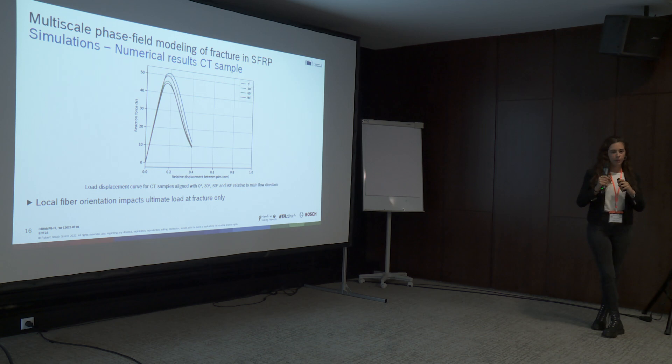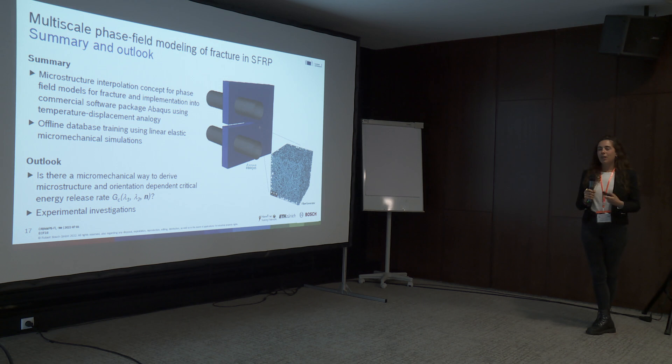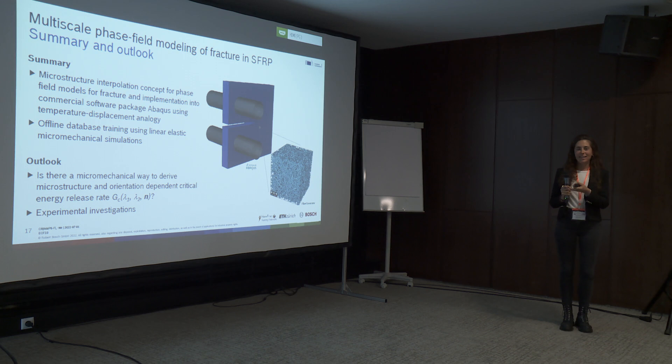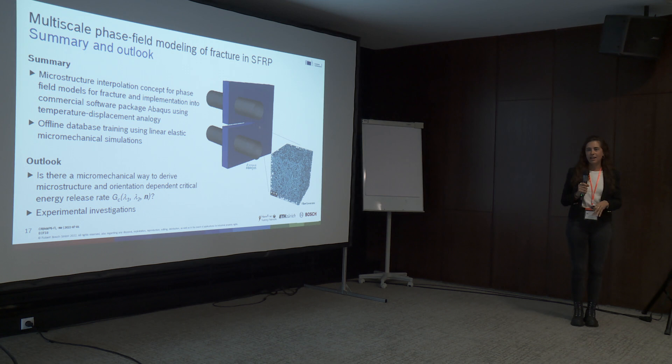Since the elasticity is anisotropic, stresses are higher in regions with higher fiber orientations. The pins are displaced 0.2 mm up and 0.2 mm down for a total displacement of 0.4 mm, and we can already see different reaction forces depending on fiber orientation relative to loading. In summary, the interpolation concept is the key point of this work, and the offline database training approach is novel for short fiber reinforced polymers. Thank you for your attention, and thanks to the NewFrac project.